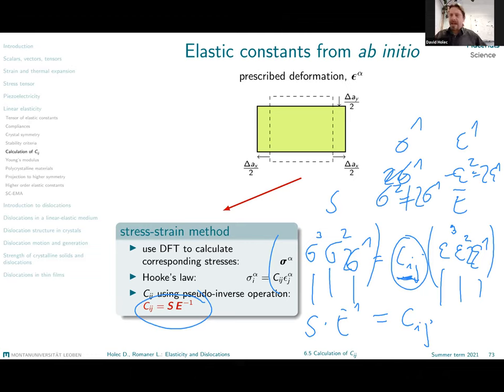In that case, I will not be able to calculate the simple inverse of this matrix. And thereby, I need to calculate the so-called pseudo-inverse. In other words, my matrix of elastic constants will not absolutely perfectly fulfill the relationship that I have here, will not fulfill Hooke's law. Because for doubling the strain, I should get a slightly different stress. This is how it should work.